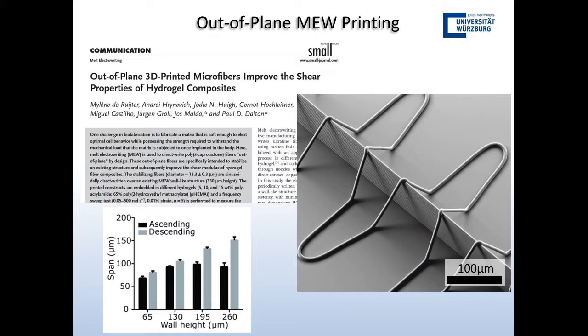So this, for example, depending on the wall height, the descending fibre would have a very defined landing spot. So even if something was on the surface already and we were doing melt electro writing, we were getting very, very reproducible structures coming from that.